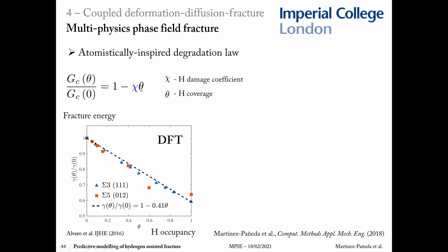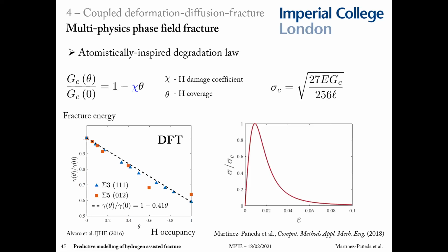The hydrogen diffusion will tell you how big the theta is, and then you get automatically the variation of the fracture toughness. And this is a similar approach, I must say, to the one championed by Michael Ortiz in cohesive elements. And in phase field models, there's a direct connection between the phase field length scale and the strength and the toughness. You can see it here. So that if you run a one element model, you get the following stress strain curve, which resembles a cohesive zone traction separation law.